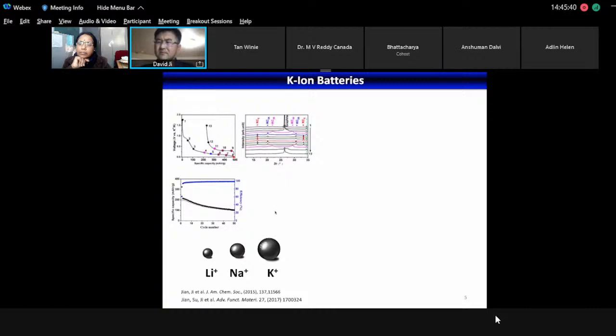Although potassium is a lot bigger, it is probably going to provide something that sodium cannot afford. For example, having the ions stored in graphite, right? So we tried it. Everybody says it's impossible. You cannot put potassium ions in graphite. But it's a simple experiment, and we did it anyway. It works pretty well, with the staging phenomenon. You have graphite, stage 3, stage 2, and stage 1. Then, reversibly, you can remove potassium ions from stage 1, 2, 3, and back to graphite. It's quite reversible.